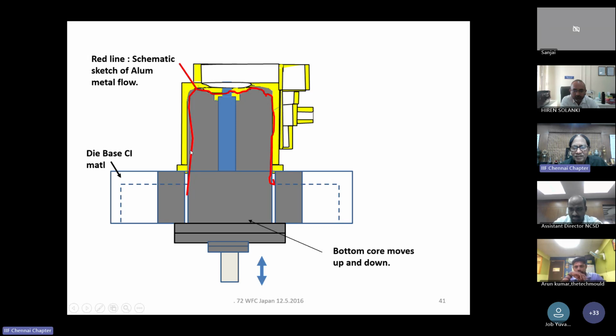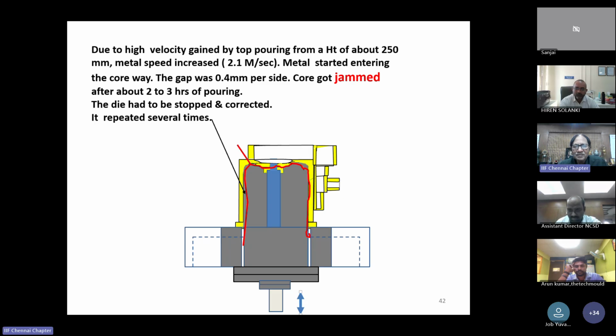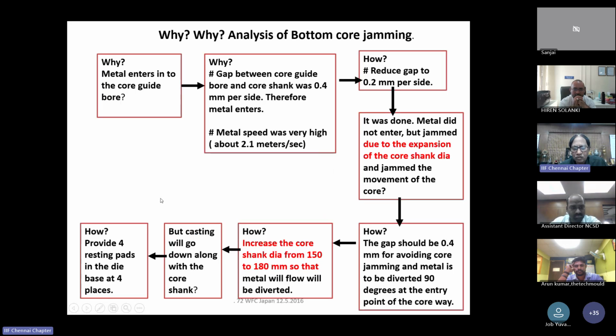So how to solve this problem? Because once in about 2-3 hours, every time you have to dismantle the core and then remove the aluminium there. The metal speed was calculated by the formula root of 2gh, by gravity, 2.1 meters per second. So the gap is 0.4 per side. And we thought, why not make it a little less so that metal won't go.